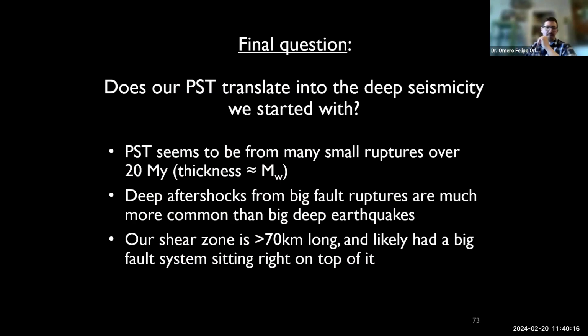And so when we think about that, and we think about a little bit of the work that has been done that tries to correlate the thickness of pseudotachylite with a moment magnitude, you end up with these are little events, assuming that you can even make that assumption in the first place. But they did this in Italy as well, on a beautifully exposed thing in the Alps. But the idea is, right, unless your pseudotachylites are massively thick, then they're showing you really small moment magnitude events, which also kind of makes sense in this setting.